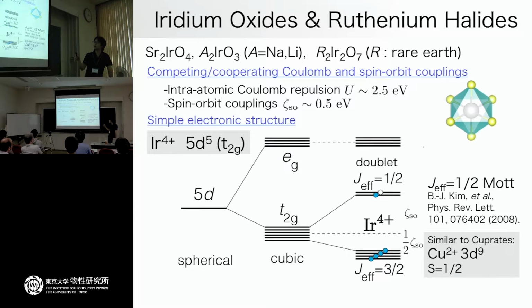And then the d orbitals of the tetravalent iridium atom split into the t2g and the eg under the cubic environment. And in addition to that, if you have spin-orbit coupling, then this t2g manifold is split into a doublet and a quartet. And in the tetravalent iridium ions, we have one hole here. So in this sense, this is a spin-1/2 system. Or in this community, we call this state the J-effective 1/2 state. And in some sense, this state is a relativistic generalization of the cuprate doublet in the copper divalent ions.